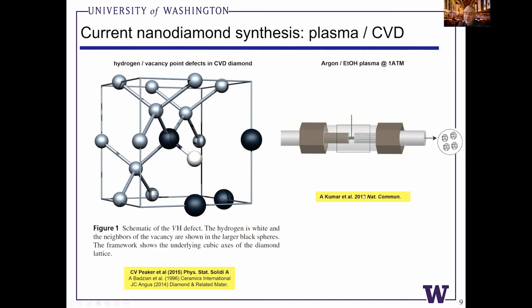There's another paper I wanted to refer to that was published back in 2017 in Nature Communications that claimed that you could grow nanodiamonds using ethanol in an argon plasma at atmospheric pressure. And we've tried to reproduce this paper, and it's been really challenging in our hands, at least. We've not been able to reproduce growing nanodiamonds with ethanol. We've been able to make metal nanocrystals. We think that we're growing copper nanocrystals from the plasma arc power supply that just volatilizes the metal.